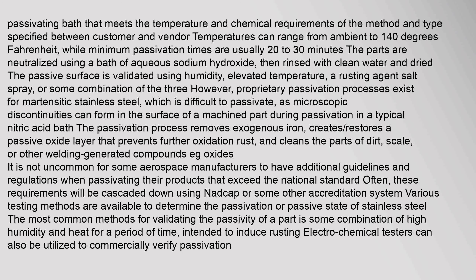The passive surface is validated using humidity, elevated temperature, a rusting agent such as salt spray, or some combination of the three. However, proprietary passivation processes exist for martensitic stainless steel, which is difficult to passivate, as microscopic discontinuities can form in the surface of a machined part during passivation in a typical nitric acid bath.